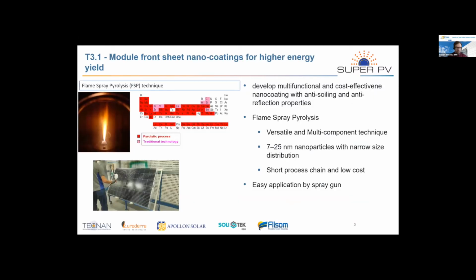So let's start with the nanoparticles, which are developed by Tecnan and Loredera. They are using a flame spray pyrolysis process to produce their nanoparticles. This is a very versatile technique which allows you to use multi-components, as can be seen here in this periodic table, which highlights the various elements you can use for this manufacturing process. It allows you to produce nanoparticles with 7 to 25 nanometer size in a very narrow size distribution. And it has the advantage that it has a very short process chain and also comes with a low cost. So, a very good low cost solution for producing the nanoparticles.